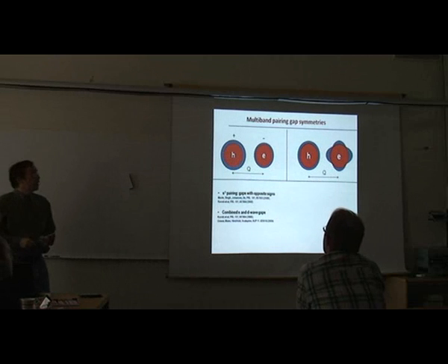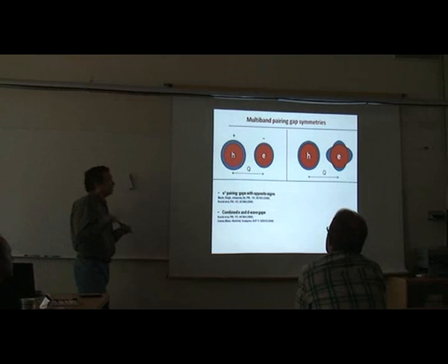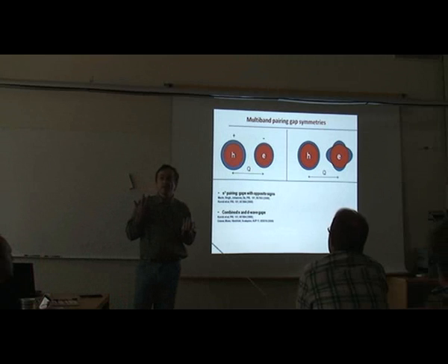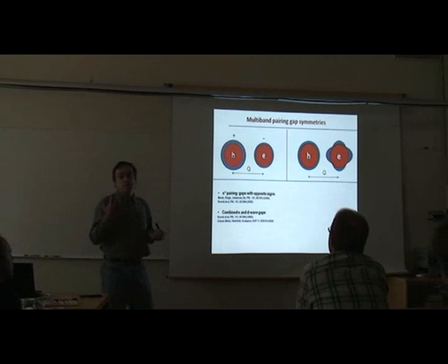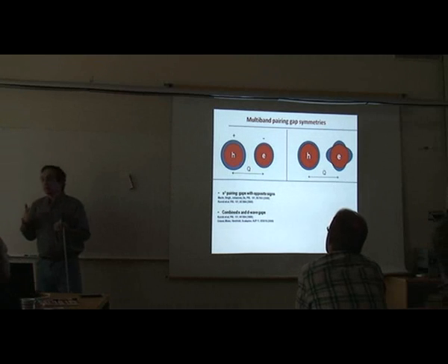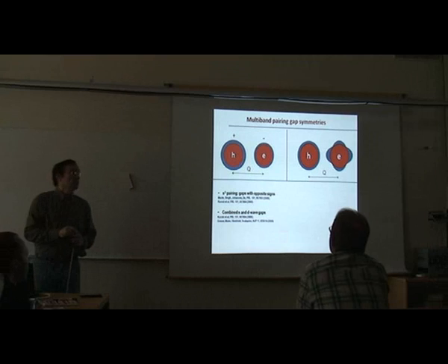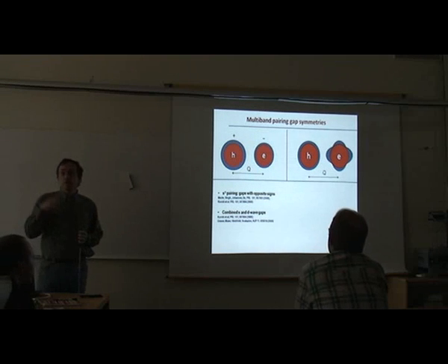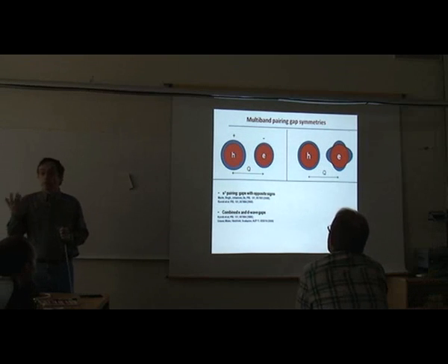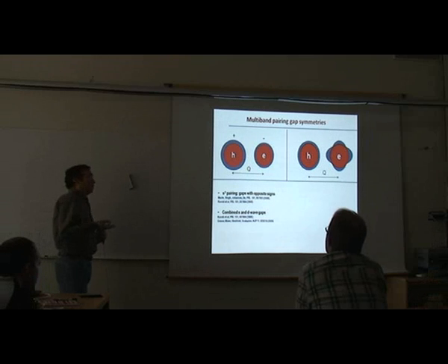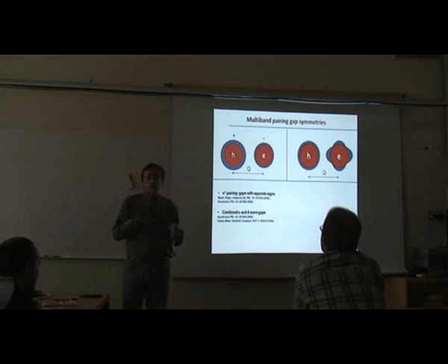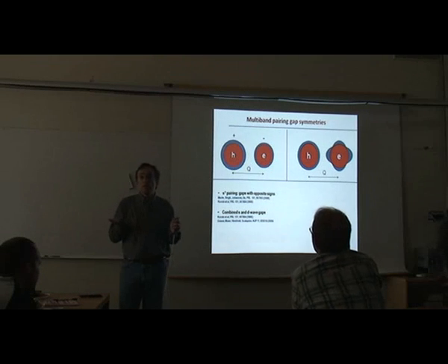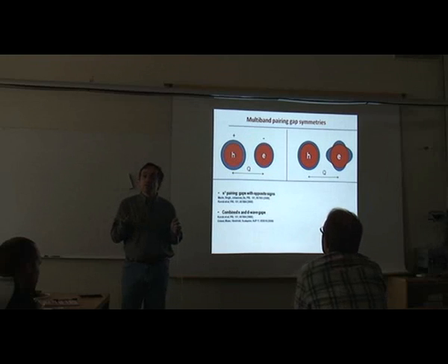Now, right away people realize that conventional electron-phonon coupling can't explain Tc that high. Because people can solve Eliashberg equations these days very easily. Everybody can calculate or measure phonon spectra, so we know everything to calculate Tc from Eliashberg. And the calculations show that Tc can be maybe 1 Kelvin or 2 Kelvin only.